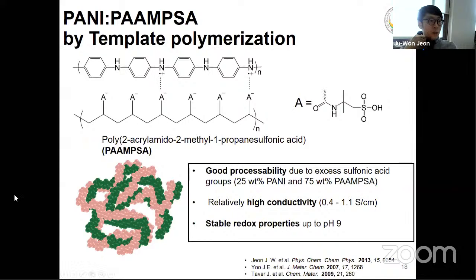By using the first approach, we adopt template polymerization and synthesize polyaniline doped by a polyacid, that is poly(2-acrylamido-2-methyl-1-propanesulfonic acid), so-called PAMPSA. It has the sulfonic acid group and it has the amide group in the functional pendant group. And this kind of polymer complex has good processability in water because of the excessive sulfonic acid group coming from the PAMPSA. And its conductivity is known to be around 1 siemens per centimeter. And it shows quite stable redox property in water up to pH 9.